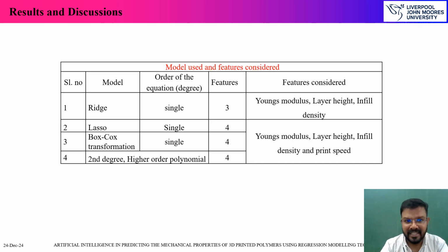Now in the present investigation, a Ridge model has been used, and the order of the equation that has been generated here is a single degree equation, and the features that are selected here are three: Young's modulus, layer height, infill density. Similarly, the second machine learning model which we also used is the Lasso single order, wherein none of the features were eliminated. So all four features were retained in both Lasso and the Box-Cox transformation, and then the second degree higher order polynomial equations. So what are those four? It's the Young's modulus, layer height, infill density, and then the print speed.